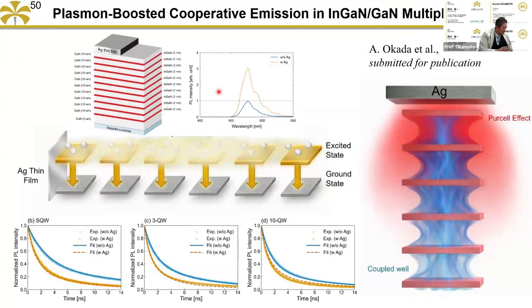I'm sorry, the time is up. That was a 10-layer multiple quantum well, and the surface resonance is a surface plasmon resonance. In this case, only the first layer was enhanced, and the others are difficult to enhance. That's why this method is not useful for such multiple layers. But by experiment, we found that even for such a structure, we can obtain more than two times enhancement.